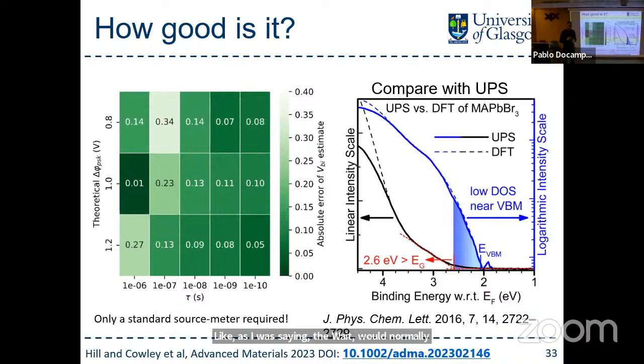I don't know if you've ever fit a UPS data set, but we do this whenever we get a paper to review. We go like, let's just pick any points on this line and see if we can get a different onset. Because it turns out that for perovskites, the density of states near the band edge is too low to get a good measurement out with UPS. So it doesn't help. So you get a big uncertainty with UPS measurements. Whereas when we do it with this pulse technique, your error tends to be about 0.1 volts, which is pretty decent.